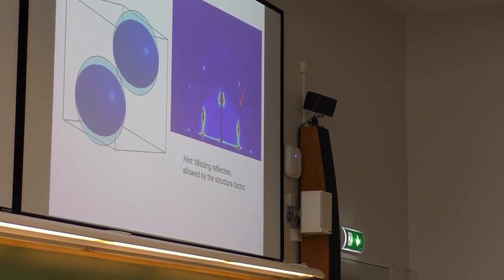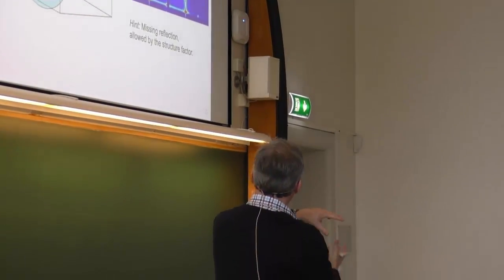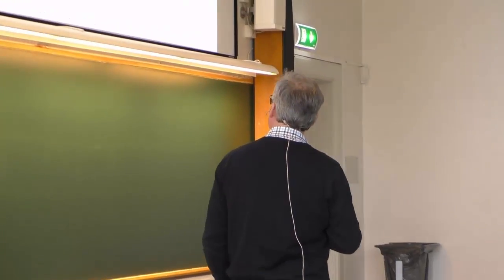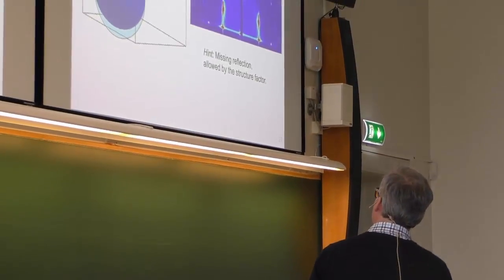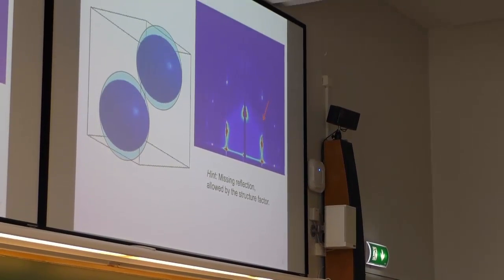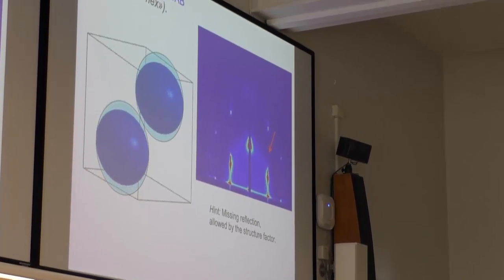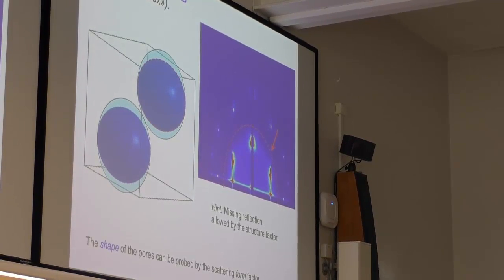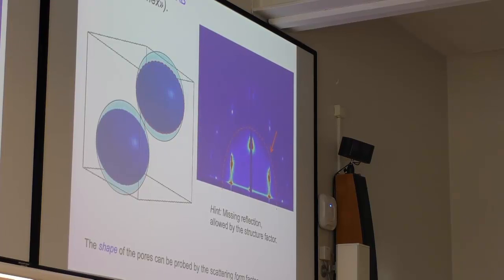So what if we can just play a bit with the form of the micelles to see if we can model this? So instead of taking the micelles in this case to be spherical, we can assume that they are slightly compressed. And if one does that, one will see that the minimum of the scattering function actually coincides with exactly these positions here. So what that implies is that we can probe the shape of these pores with a few angstrom resolution in this case, which I think is a very cute result in this respect.